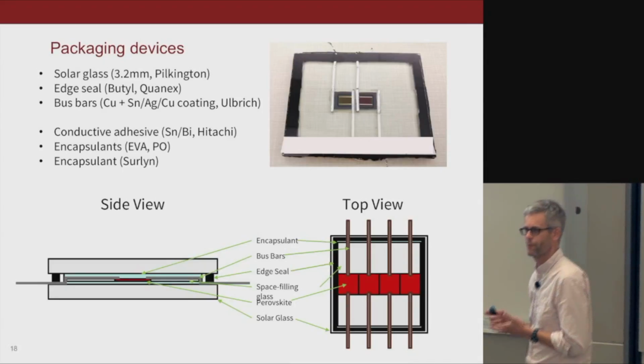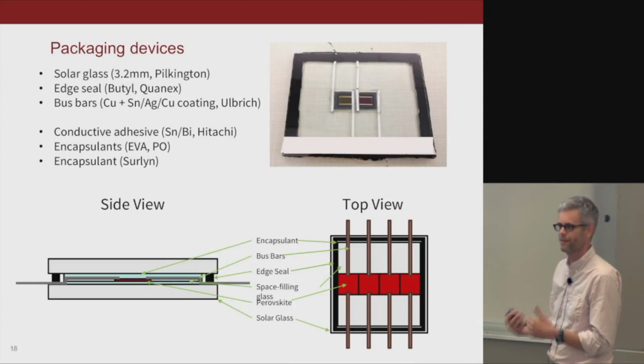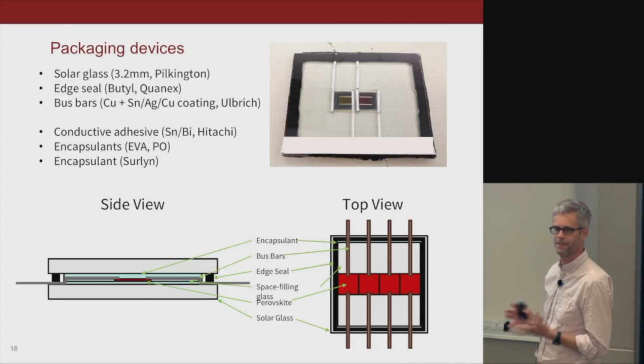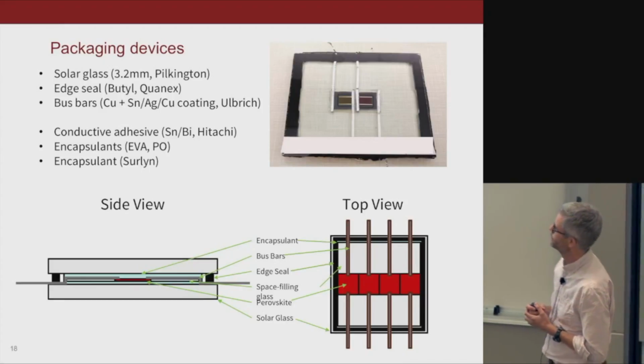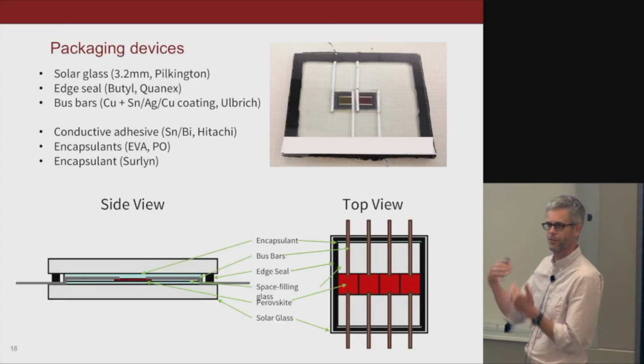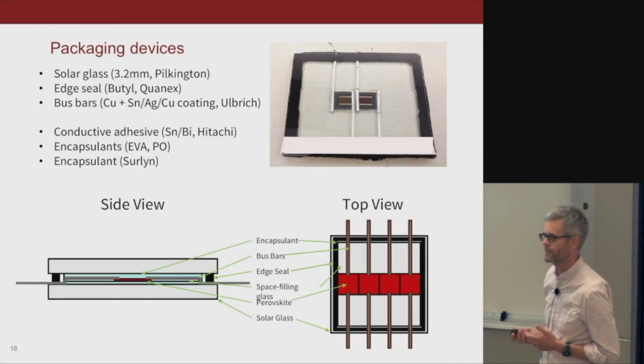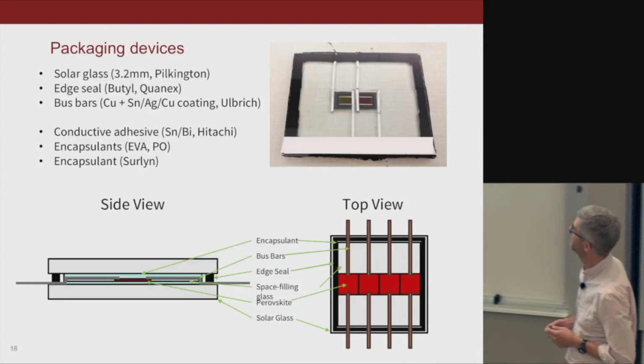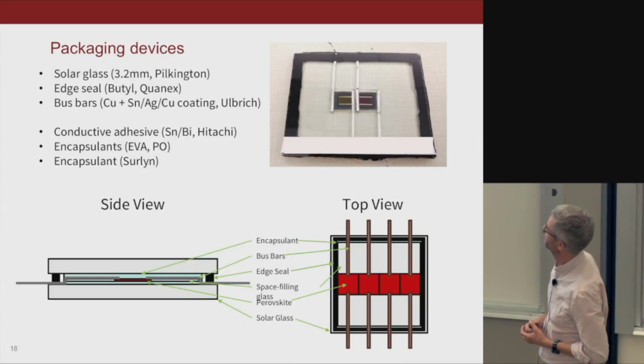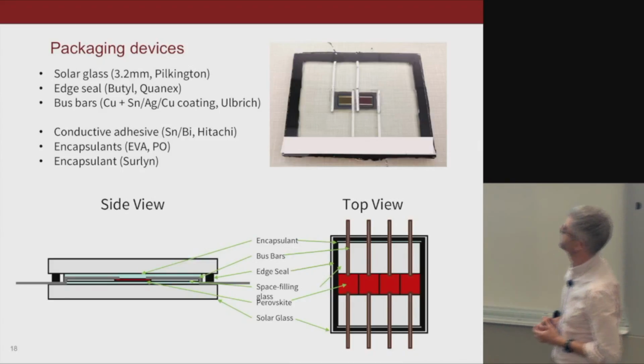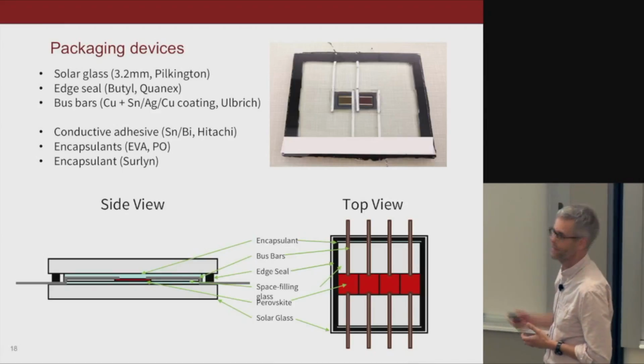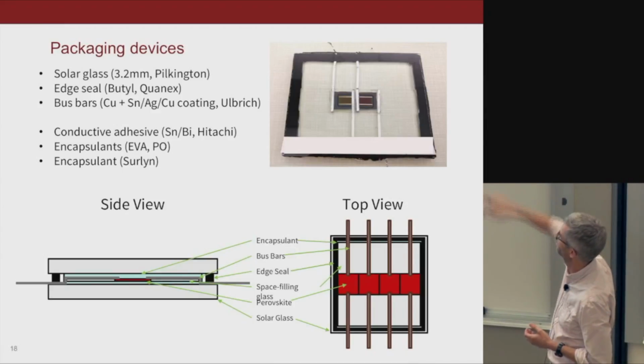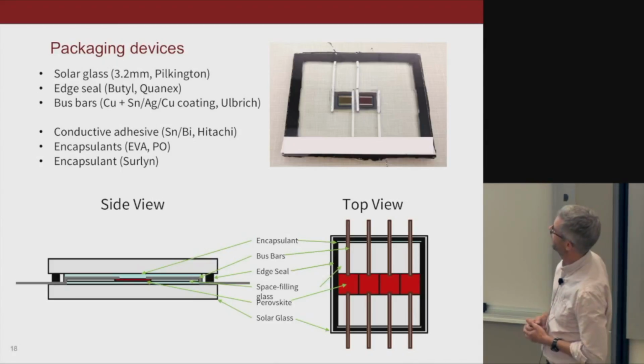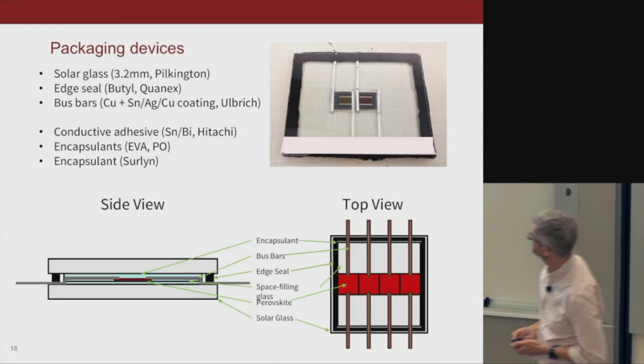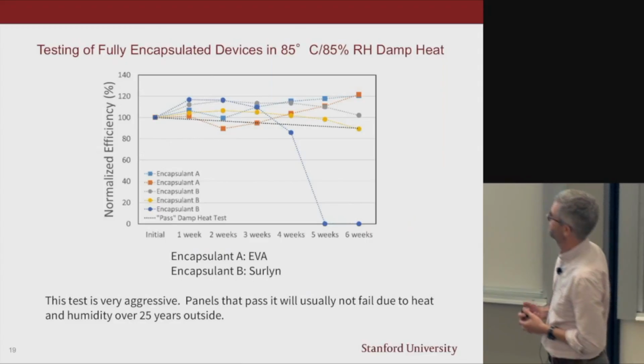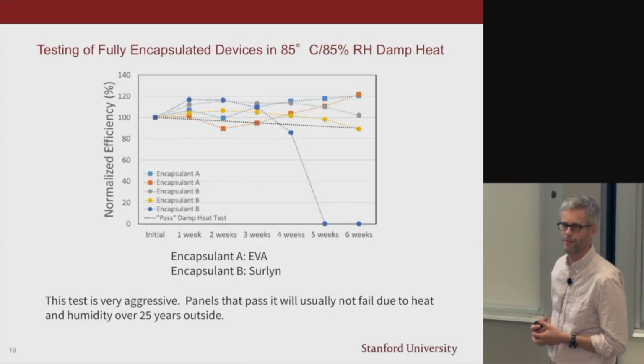We did 3 things. We replaced the methyl ammonium, which was leaving the film, with a combination of cesium and formamidinium. And then it turned out we were having corrosion with our metal electrodes. We replaced that with a metal oxide. And then we took advantage of being in Silicon Valley, and we just went to a nearby solar cell company, and they showed us how to do a proper package with a rubber edge seal. And with those 3 things, we're now able to pass the industry standard tests.